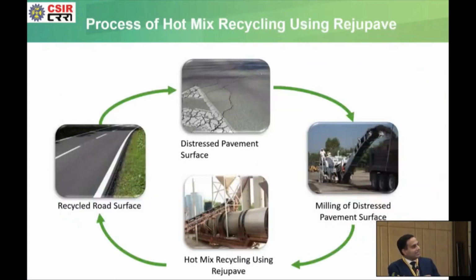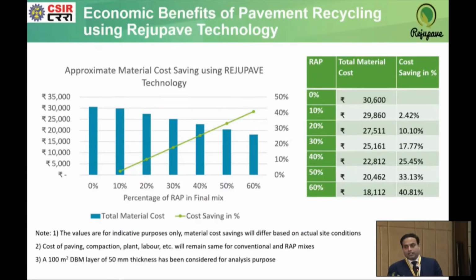So this is a typical cycle: a distressed pavement, then milling of the distressed pavement surface, then hot mix recycling using hot in plant recycling technique, and then laying of the recycled road surface. Now in terms of the cost saving, if we go with different RAP percent utilization, right from 10% to 60%, then the net saving on the per ton production of bituminous mix will be 40.81%.